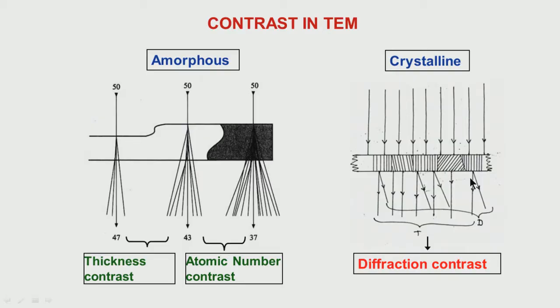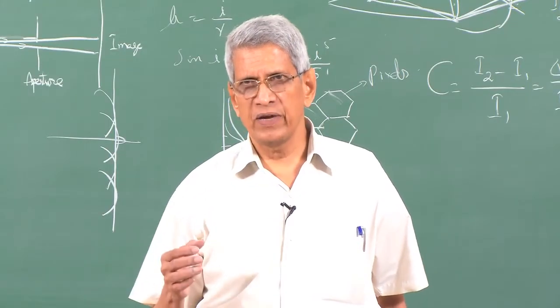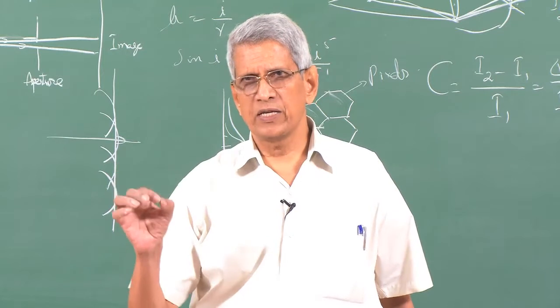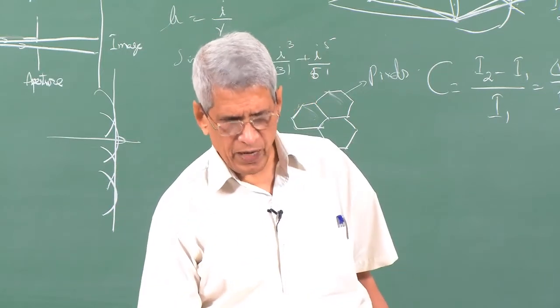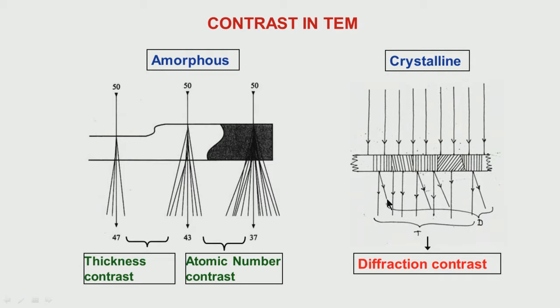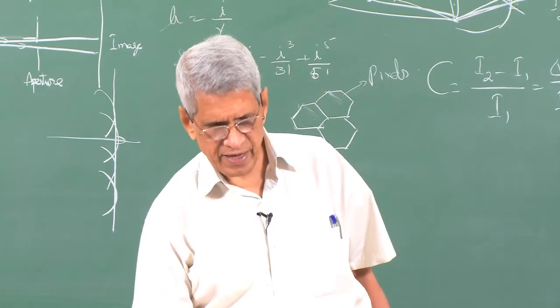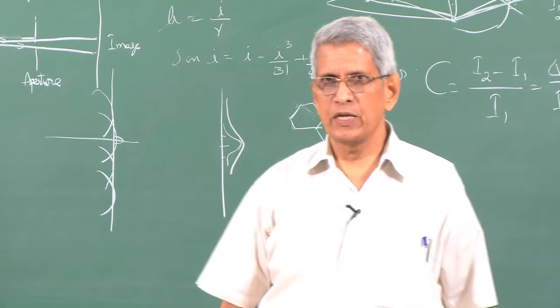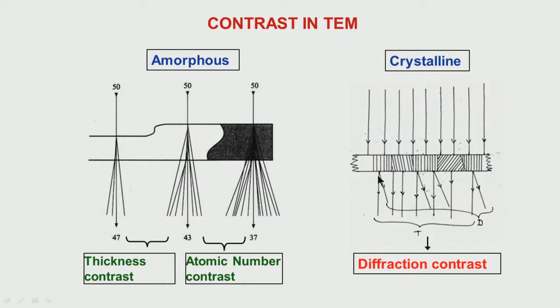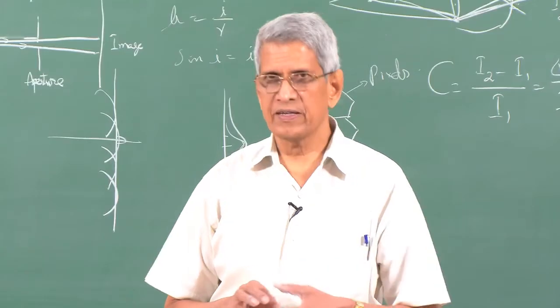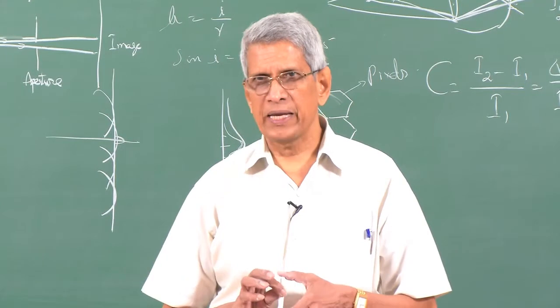Suppose some defects are present. The defects are regions where the atoms are displaced from the correct lattice site. That will also give rise to variation in the scattered intensity. So that will also come as a variation, and this we call contrast. So the contrast arises in a crystalline material due to diffraction, and this contrast effect could be very strong, much stronger than this mass thickness contrast. So in all crystalline materials, the contrast is essentially coming from diffraction phenomena.